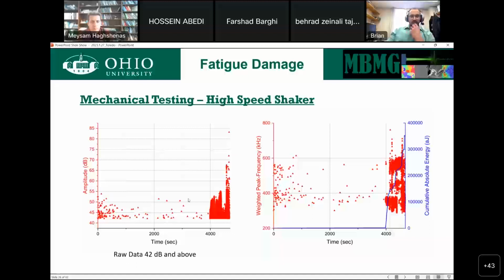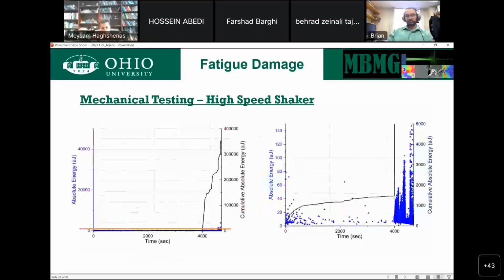And that's where we can then start looking at the data just above the line. That allows us, instead of having to deal with all of those signals, to work with a much smaller data set and still get the same basic trend information that we're looking for. And we can see more activity early, dies off a little bit before a crack nucleates and really starts to grow rapidly across the material. Not surprising for a bending fatigue test.